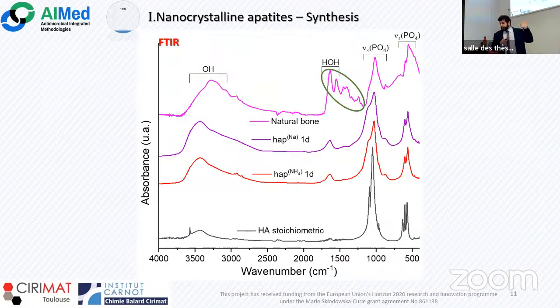Clearly, because of the low crystallinity, the spectra are not well defined. So to complete the characterization, we also do an FTIR analysis, and we can observe that the spectra have a good accordance, referring both to the stoichiometric hydroxyapatite and the bone mineral, of course, with the exception of the zone where the traces of the collagen and of the organic matrix of the bone are left.